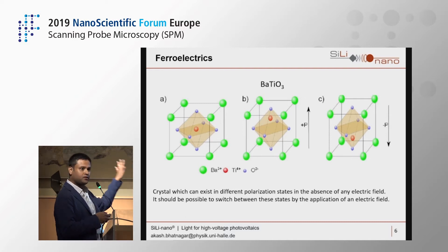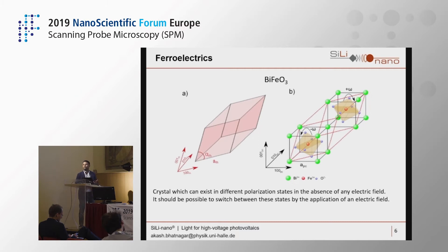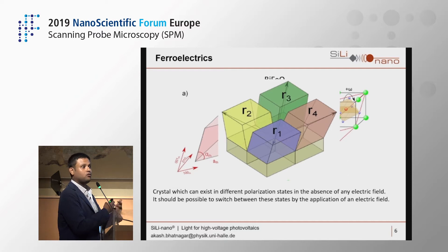This is one of the simplest systems to understand. It gets more complicated with bismuth ferrite — the material of interest in our group — which has a rhombohedral unit cell, represented as two perovskite unit cells. The polarization is along the [111] direction, and because of this you can have eight different variants of domains — a distorted cube elongated along [111] representing each variant. This is how polarization variants work in this material, and therefore we need PFM to determine which domains are present.